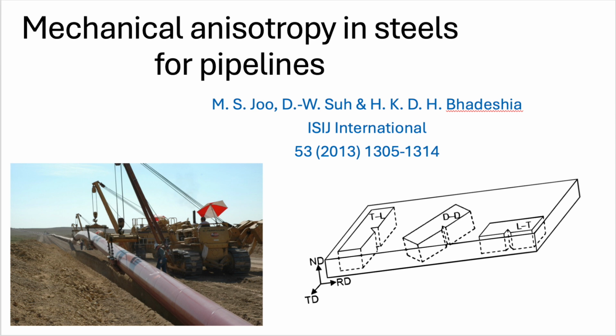Yes. Now, because of how spiral-welded pipes are made, winding a rolled steel plate into a spiral, welding the edges, that critical circumferential direction often aligns with the direction on the original plate that has the lowest toughness and strength due to anisotropy. Oh, wow. So the direction experiencing the maximum load is potentially the weakest direction in the material itself? Precisely. That's the design nightmare. You're putting the highest demand right on the material's weakest point. It significantly increases the risk of fracture initiation.